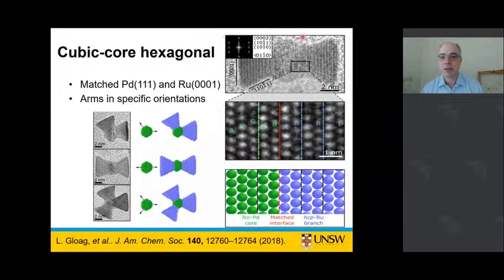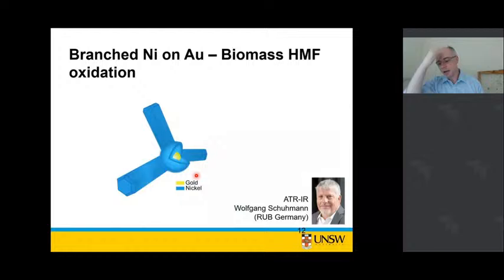And if we have a look at the high resolution TEM image and we have a look at the interface between our palladium core and our ruthenium branch, we can see that we have our ABC cubic packing from our palladium, and then we're switching when we get into our ruthenium to our HCP AB packing as we have a look at that interface.